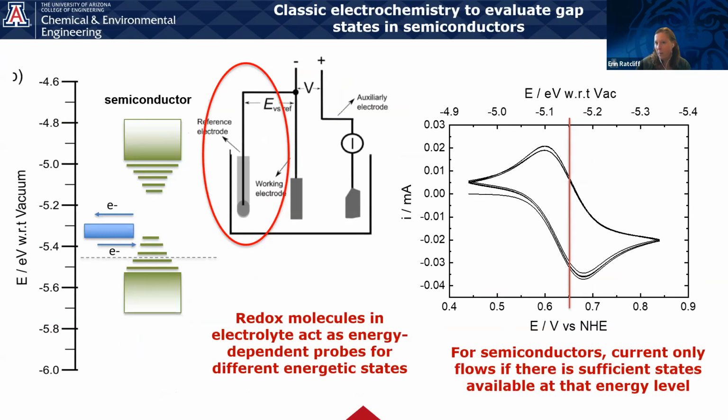We know that iodide and bromide have different oxidation potentials, so you can put iodide in and you can put bromide in. In the triple cation, those defect peaks truly go up when you spike it with a little bit of iodide, and the bromide is not participating at all. You have to basically destructively oxidize that perovskite in order to get the bromide to come out.